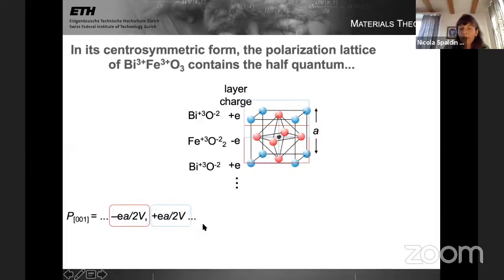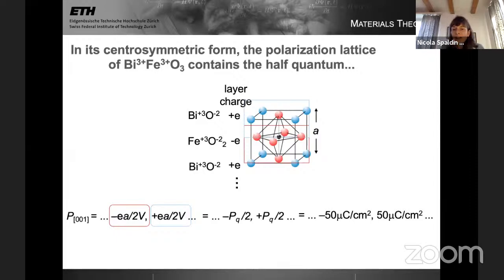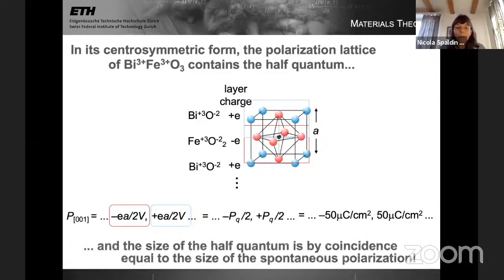My polarization is plus e times a over 2V, and if I took different unit cells, I'd get different numbers. They'd all be spaced by the polarization quantum, and this first number is half a quantum, and so on. If I put in the actual numbers, I find that half the polarization quantum is 50 microcoulombs per square centimeter. So the polarization lattice of bismuth ferrite in its centrosymmetric form contains 50 microcoulombs per square centimeter. This is the half quantum.